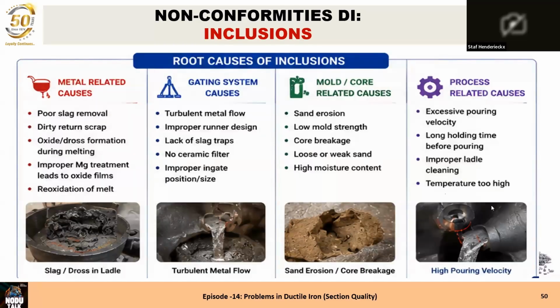So the root causes of inclusions, we see the metal-related ones are poor slag removal. If you have a lot of dirty return scrap that you use for your melting, the risk is very high that you will get it. Oxide and dross formation during melting, that's one thing, but if you don't remove them from the ladle before you pour, you will get a problem. An improper magnesium treatment leads to oxide films. That means if your magnesium is very high compared to the residual sulfur content that you have, dross is very, very high, and to a lesser extent reoxidation of the melt. Because with the magnesium present, the reoxidation will be very little. It's mainly the magnesium and poor slag removal from the ladles.